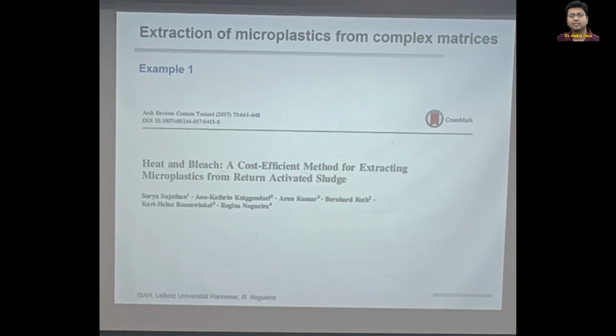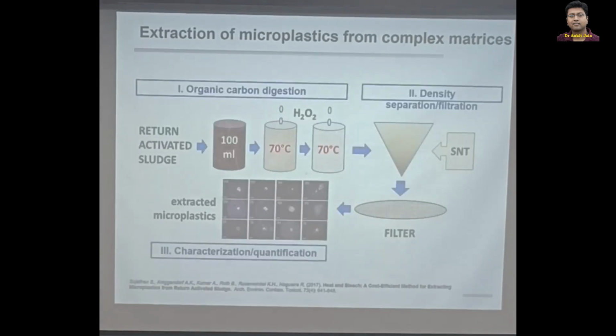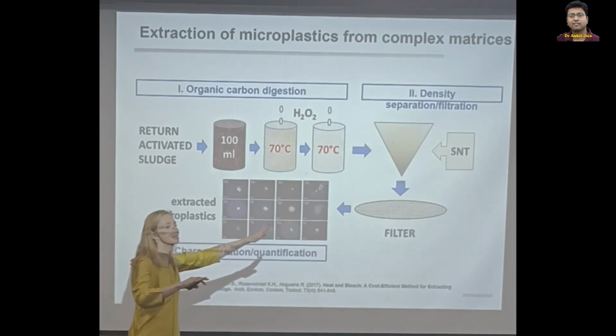Okay? And what did we do? This is here very briefly. Here you can see again the three steps that we used. We had our sludge. We contact the sludge with hydrogen peroxide. This is an oxidation agent that will degrade the organic matter. We raise the temperature to 70 degrees because we don't want to wait 1 week for the process. Afterwards, we separate the plastics using density separation, and we collect the plastics in one filter. Okay. Then we have our sample to be analyzed.